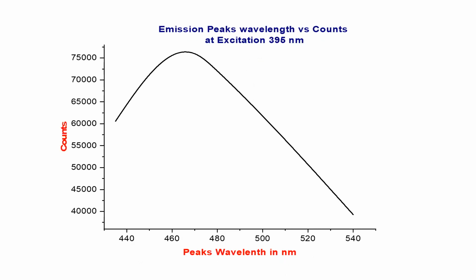But when we excite with 395 nanometer, surprisingly I found only one peak, and that peak comes at 467 nanometer. So it means we can put our analysis on the basis of different excitation values.